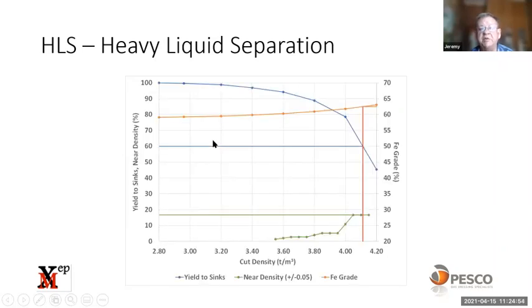There's another way which gives a bit more information. What we do is we plot the cut densities on the x-axis. On the y-axis, we plot yield to sinks and the near density, we'll go into that. And then on the other y-axis, we've got Fe grade. So if we look at yield to sinks, there's my yield to sinks curve, which is a blue curve. Then your Fe grade goes from just below 60, we said it was a 59, up to there, that's your cumulative grade. And then here's the near density curve, which is your plus or minus 0.05 of your cut densities. That's the amount of material plus or minus 0.05 above and below your cut density.